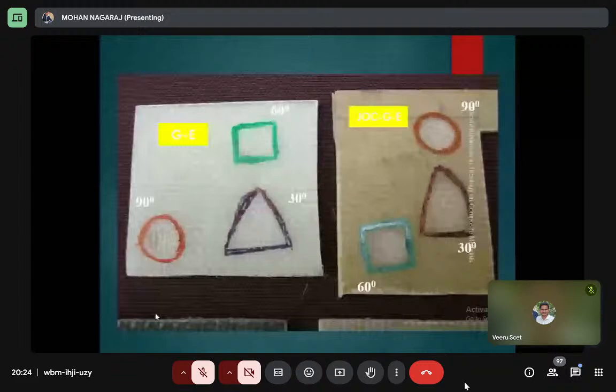Here the pure JOC composite gives a very good erosion rate compared to the others. So here we have the erosion rate at different velocities. Velocity means the silicon particles are hitting the specimen at different velocities. The lower the velocity, the lower the erosion, and the higher the velocity, the higher the rate you are observing in this diagram.